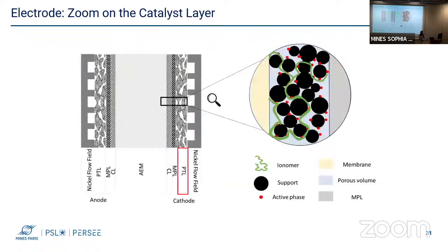The electrode usually consists of a porous transport layer, optionally a microporous layer, over which the catalyst layer is deposited. The catalyst layer consists of the catalyst support and the components of the active phase that are connected together using an alkaline exchange ionomer. In addition to acting as a binder, this ionomer provides pathways for the transport of hydroxide ions inside the catalyst layer and into the membrane.